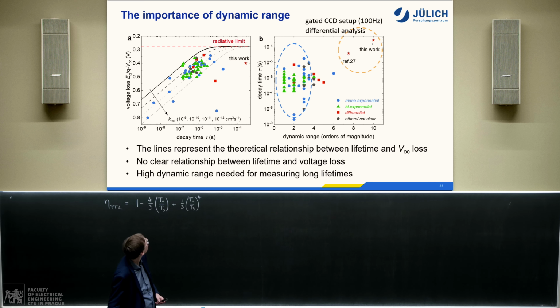It was here. Okay, I can't quite see the quantum yield. We need to calculate it. The difference between here and here gives the quantum yield. So it's approximately 0.5%, half a percent. It's an order of magnitude worse, approximately.